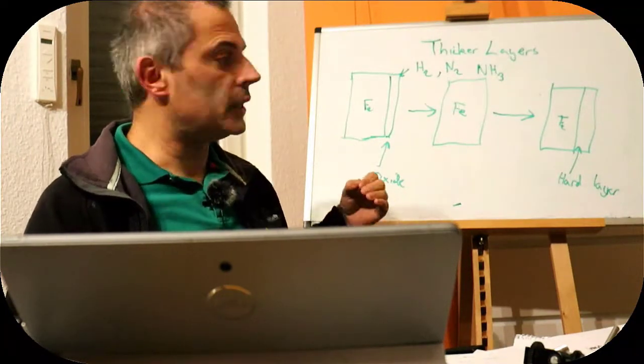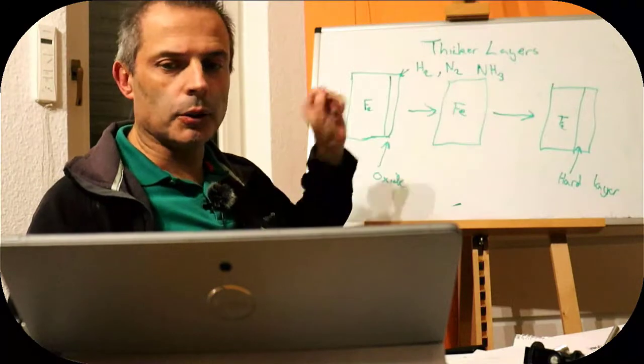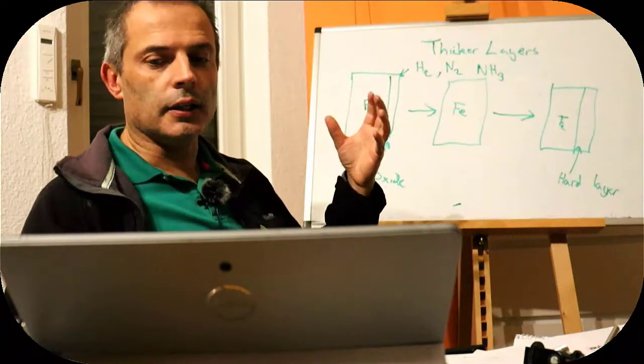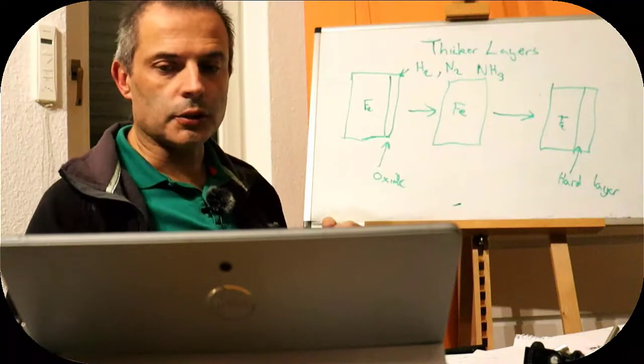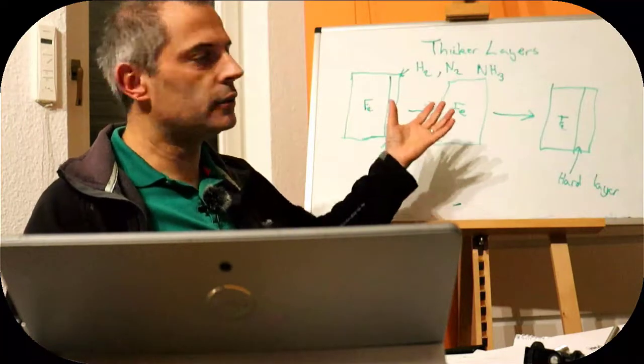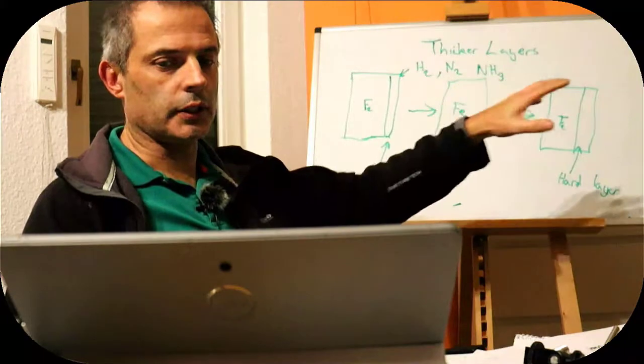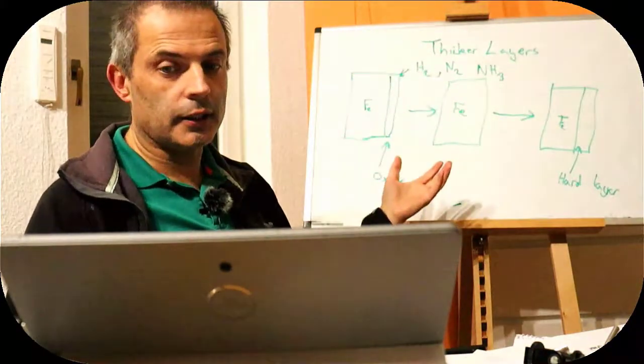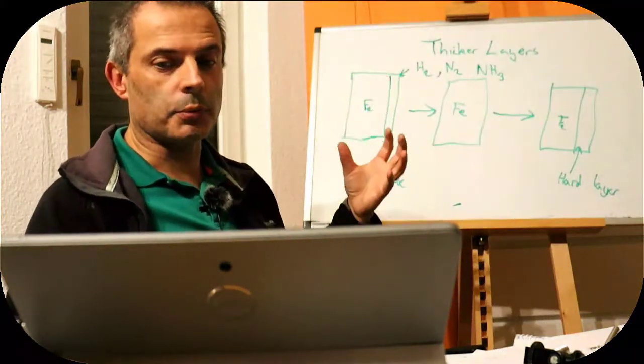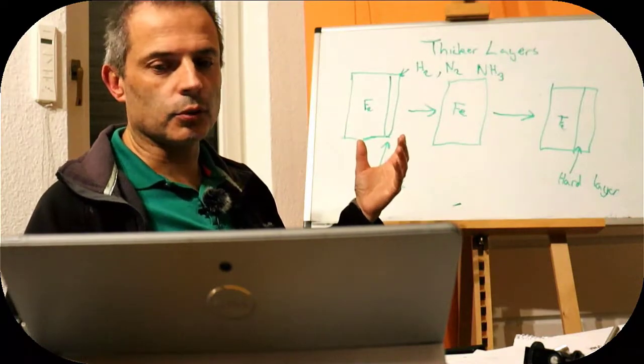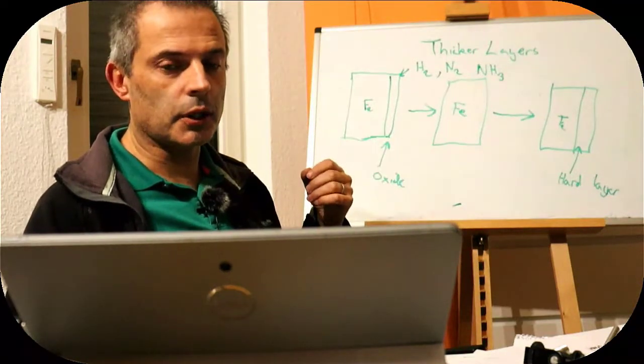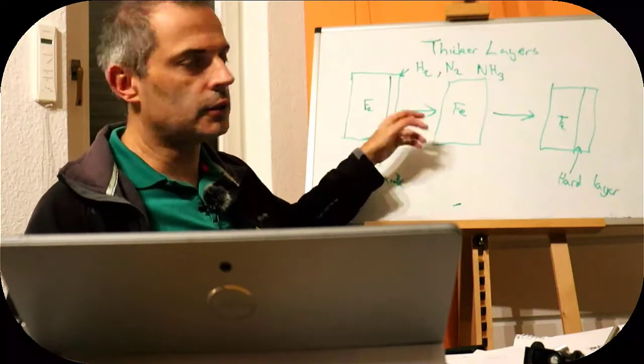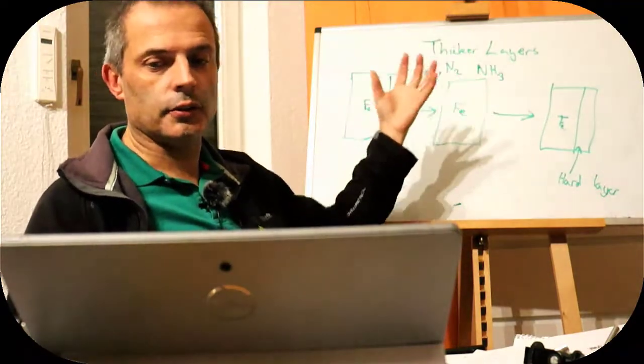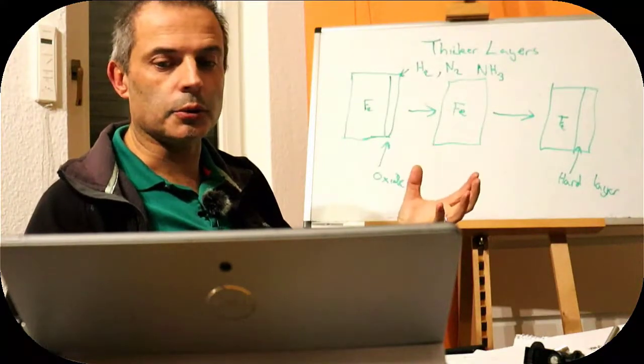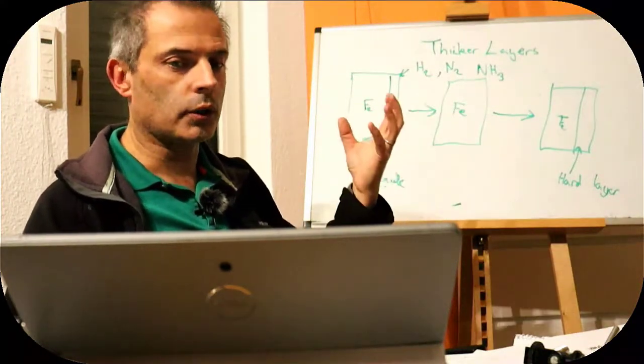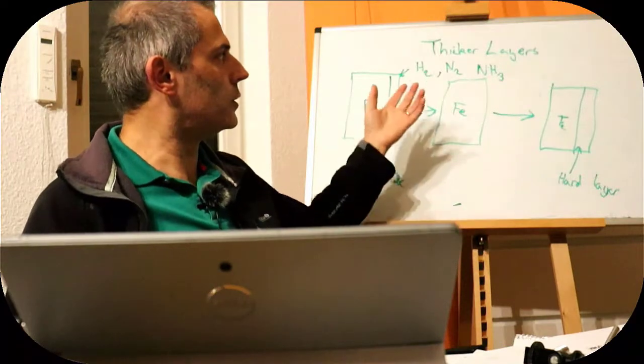A different way to get the nitrogen or carbon, but mostly nitrogen, into the metal is using a plasma. So we've discussed plasmas before. We can make an ion out of the nitrogen and we can shoot it into the metal. That's very handy, and it also opens up a new window, because first of all we don't need to heat up our sample very much, and then it will stay close to the surface. We can control the energy of the ions by accelerating them to a chosen voltage, so we have more control parameters than we did before with just heating it.